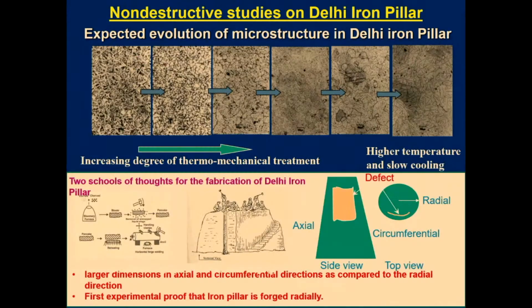And if I arrange these microstructures in a particular fashion, notwithstanding the locations, you can see that when we go from left to right, there is an increasing temperature and slow cooling rate for the corresponding microstructures. You can see the continuous variation in the different types of microstructures that are obtained depending on the temperature, cooling rate, and strains, that is, how much hammering is done.